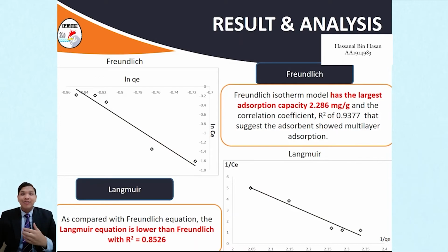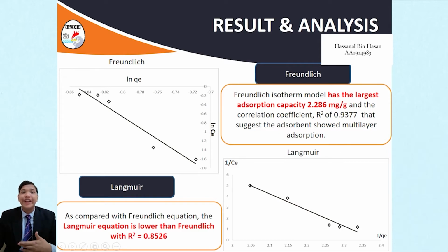Besides that, there is also the result and analysis of the isotherm models, which are the Freundlich model and the Langmuir model. The Freundlich isotherm model has the largest adsorption capacity, which is 2.286 mg per g, and the correlation coefficient R2 of 0.9377 suggests the adsorbent shows multilayer adsorption. Compared with the Freundlich equation, the Langmuir equation is lower, with R2 equal to 0.8526.